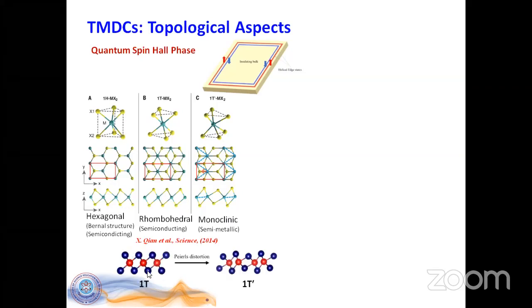So this is one layer example of 1T, where there is uniform distance or separation between the transition metal elements. Whereas after it undergoes a distortion, which is a Peierls-like distortion, there is dimerization of the molybdenum atoms, and this gives rise to a new structure which is called the 1T prime, and this happens to be in the monoclinic phase. Now, in terms of their electronic properties, the H and the T phases are usually semiconducting. Sorry for this spelling. And the 1T prime is semi-metallic.